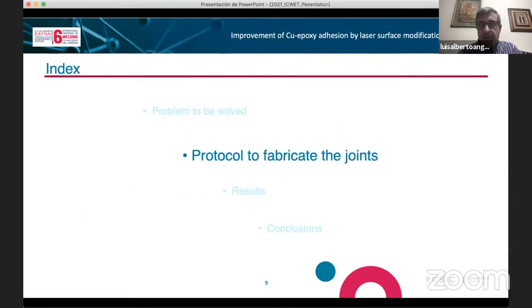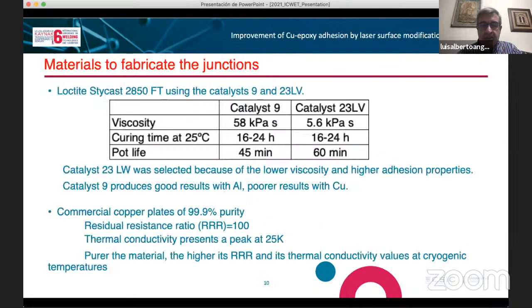The protocol that we have been using to fabricate the joints is, okay, we have been using Loctite Stycast 2850 FT. We checked two catalysts, 9 and 23LV. The 9, as I told you, produces good results when we use aluminum instead of copper. But with copper, the results were not so good, as I have been showing you before. The difference between both catalysts is the viscosity and mainly the pot lifetime, that is longer in the case of 23LV. For this reason, in all the results I'm going to show you, we have been working with this catalyst instead of 9.